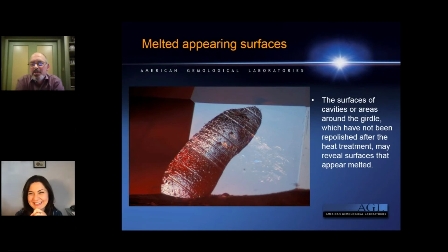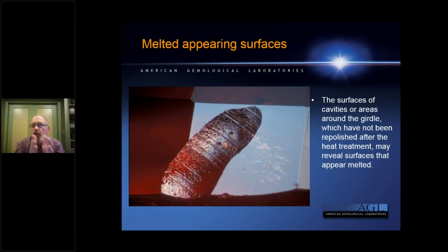So yes, this is when it comes to what you want to do. When you're heating under reducing conditions, you are also wanting to dissolve inclusions of rutile because you're wanting to facilitate the pairing of iron and titanium. So you're diffusing hydrogen in to help facilitate that process of creating this intervalence charge transfer. When you're heating rubies, you're heating under oxidizing conditions, so pure O2 kind of conditions, because here you want to break this charge transfer. So this is why furnaces like what I had shown are very effective. They significantly changed what can be accomplished when you're heating corundum, because you can alter or modify between oxidizing conditions and reducing conditions. So I hope that answers the question that the gentleman had.